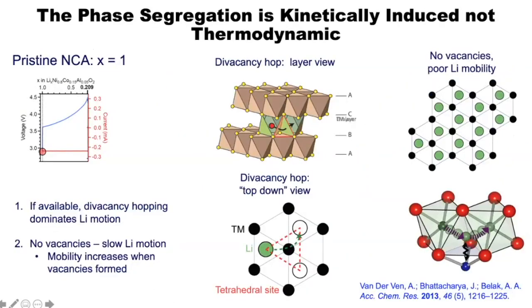So let's try and pull all this together and go back to the idea of how lithium ions move in these layered materials. So remember, we're getting hops from octahedral sites across through this intermediate tetrahedral site. And the hop becomes allowed, and this is work nicely summarized in a review article by Anton van der Ven, when you have a divacancy mechanism nearby. So the hop will go to a tetrahedral site, and when there are two vacancies here, the repulsion for the next part of the hop process is removed. So you imagine you start off with your NCA material, you've got almost a full lattice, and there are very few vacancies, so the lithium mobility is very poor.